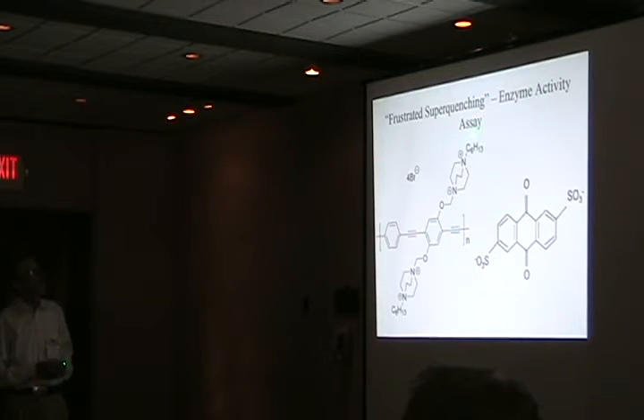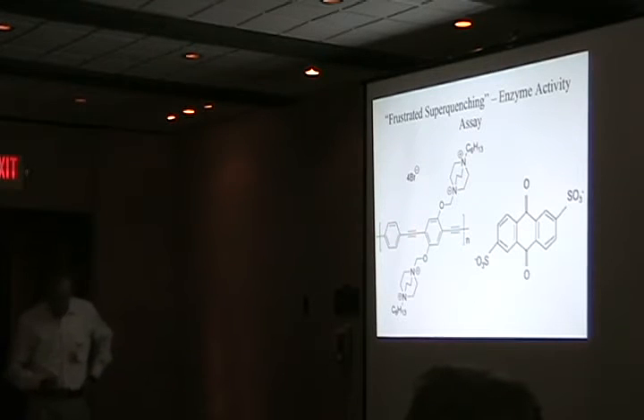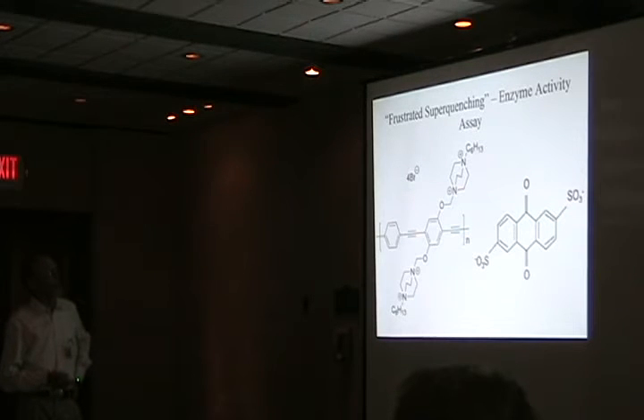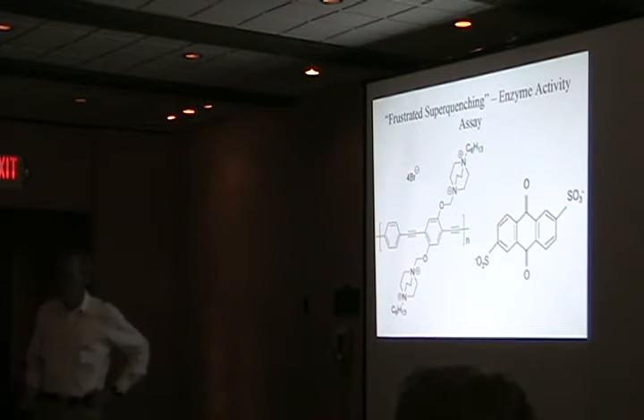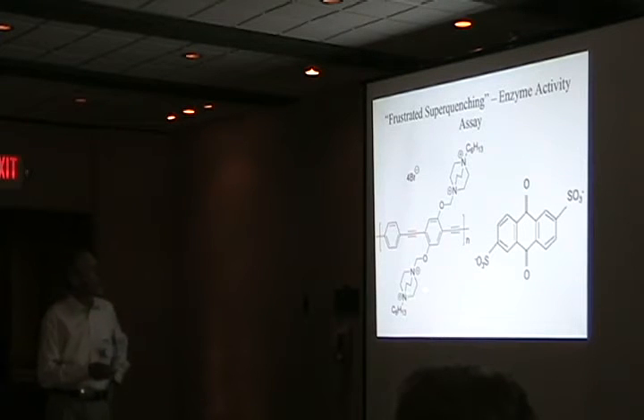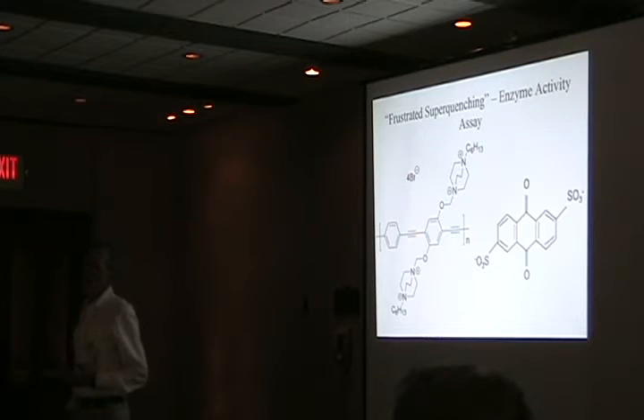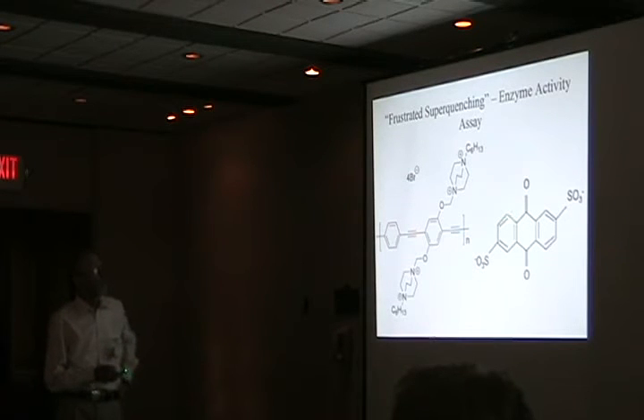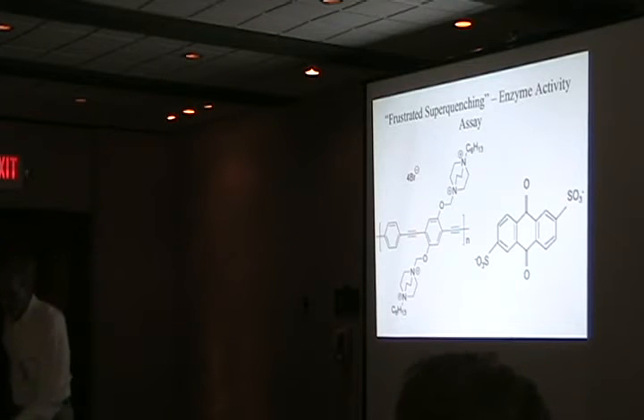This is an enzyme activity assay, and we use this adsorbed polymer. We can use this, or we can use a single cationic group, a trimethylammonium group that's a little farther away from the polymer. But this forms a very nice adsorbed layer onto various microsphere supports, and we now look at quenching of it with this anionic electron acceptor, anthraquinone disulfonate. And what we find here is when we have this polymer on a microsphere support, we can quench effectively all of the polymer by adding just a small amount of the anthraquinone disulfonate. So the anthraquinone disulfonate associates with the polymer on the microsphere, and the fluorescence is very strongly quenched.